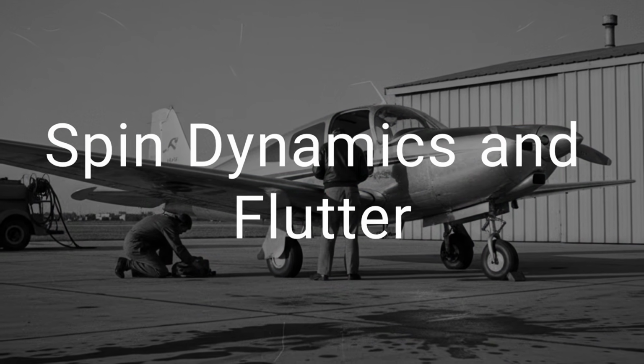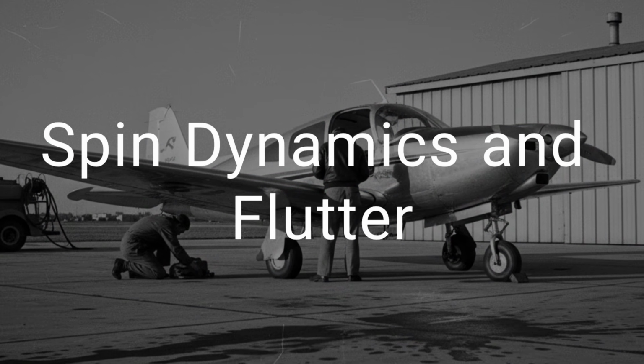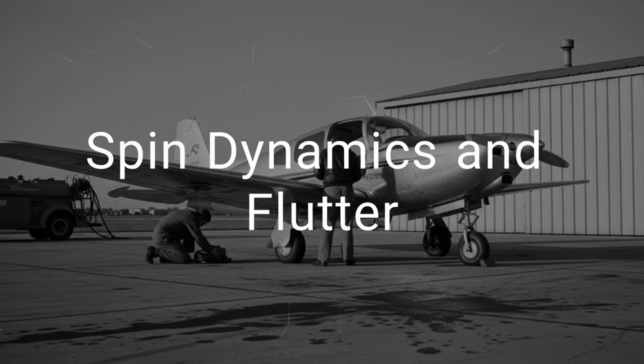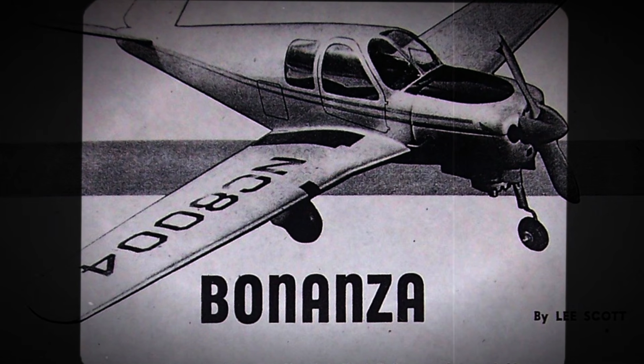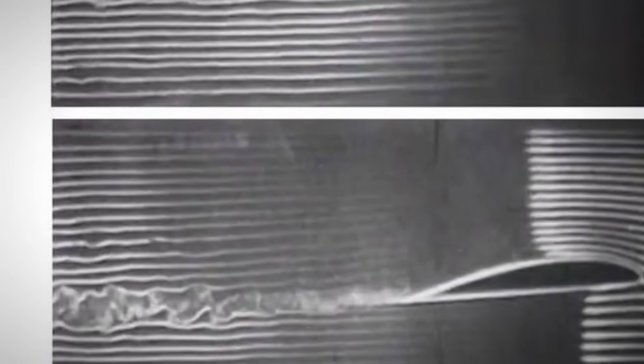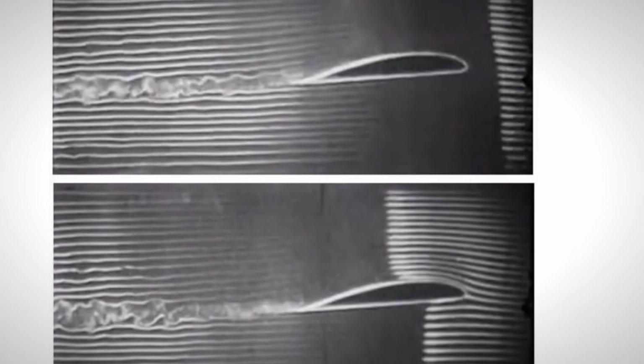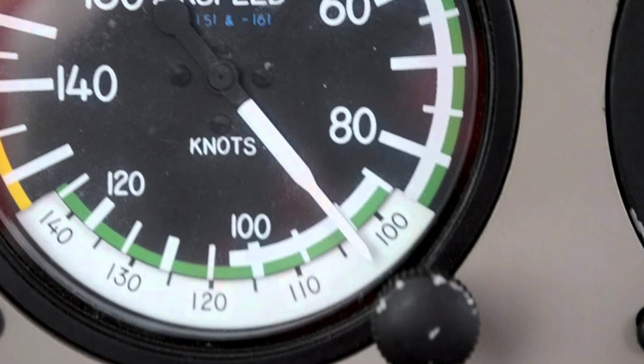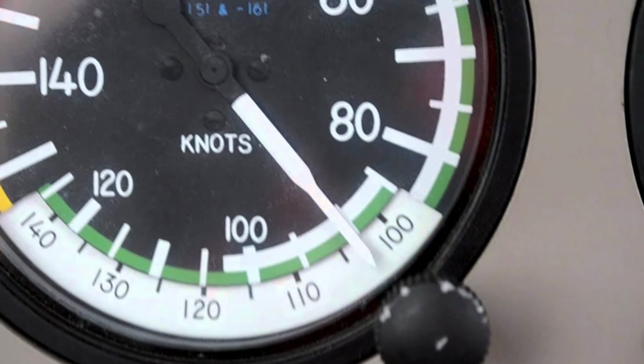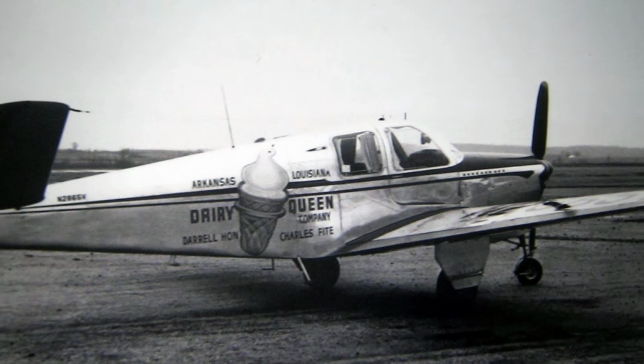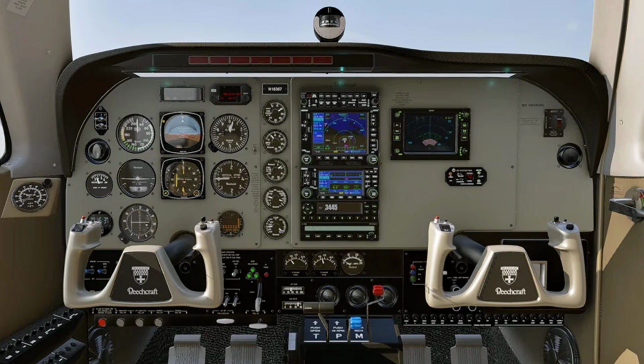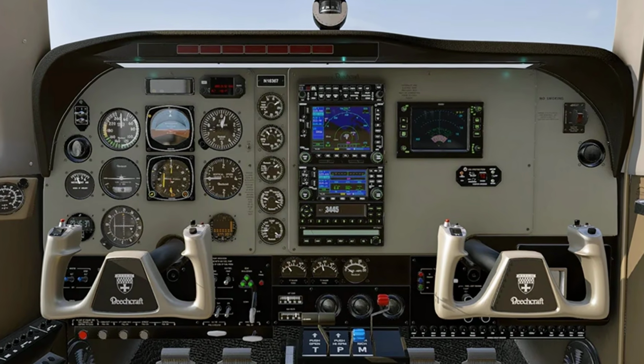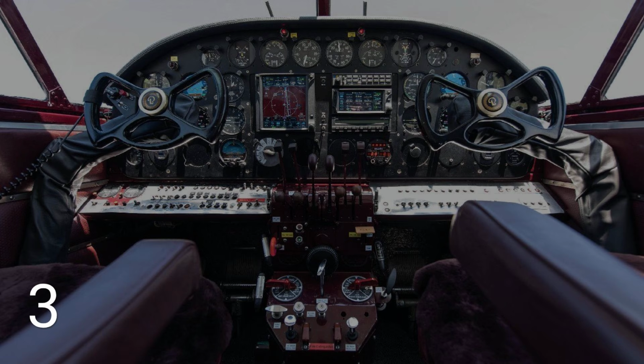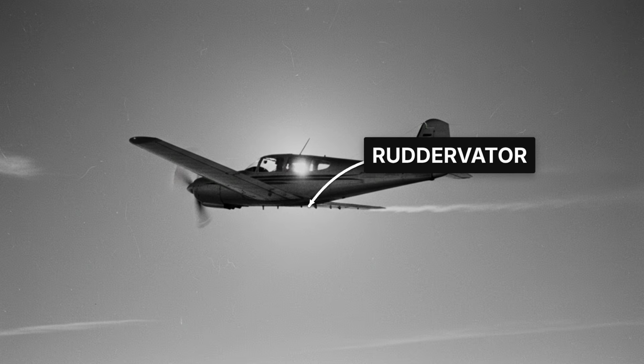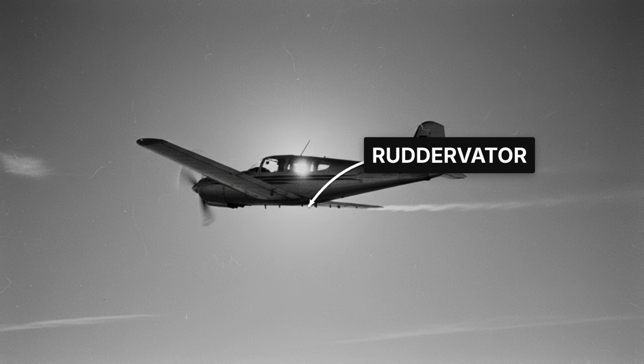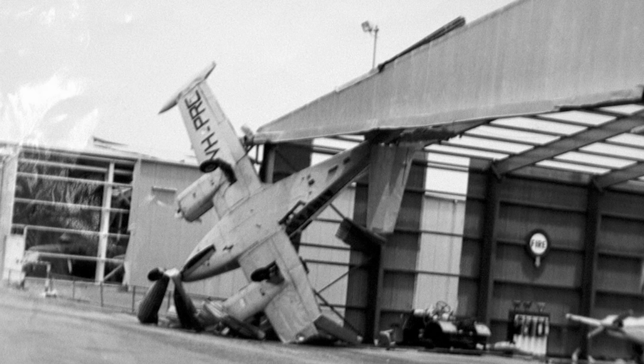Push a Bonanza V-tail past its never-exceed speed, and you do not get a warning light, you get physics cashing in a debt. The magnesium ruddervators, those featherweight control surfaces Beech Aircraft Corporation bragged about in every sales brochure, are a flutter trap waiting to spring. The moment airflow hits that critical speed, sometimes just a handful of knots over VNE, the tail starts to tremble. It is subtle at first, a vibration through the yoke, but in less than 3 seconds, the oscillation goes exponential. The whole empennage becomes a tuning fork, the frequency rising until the magnesium skin cannot keep up.